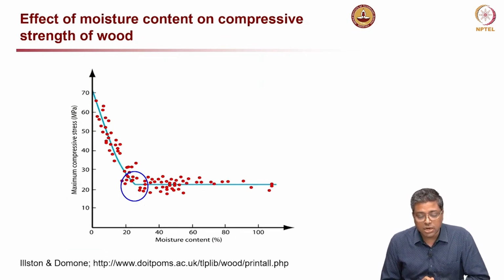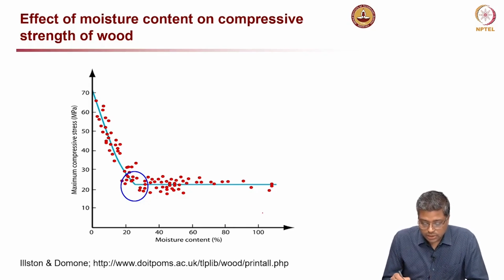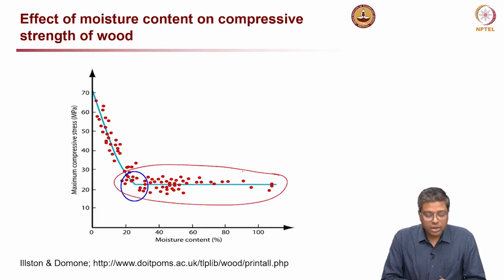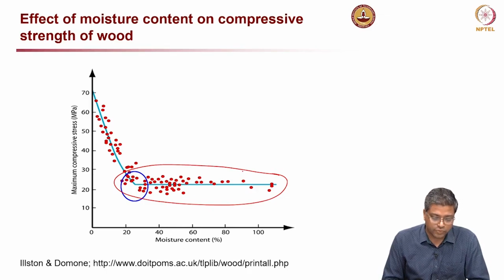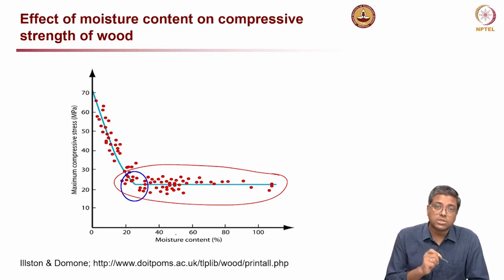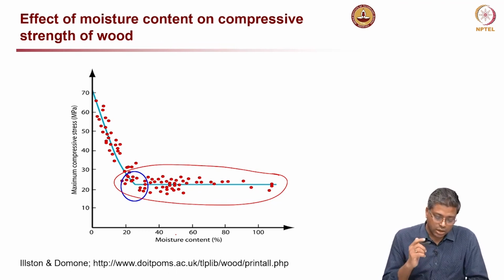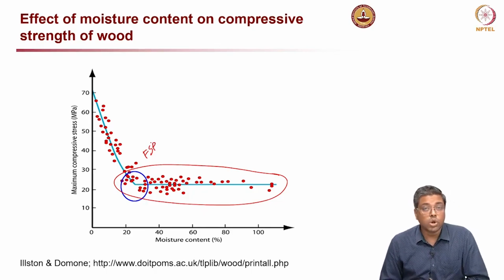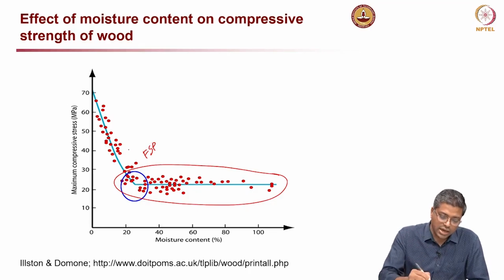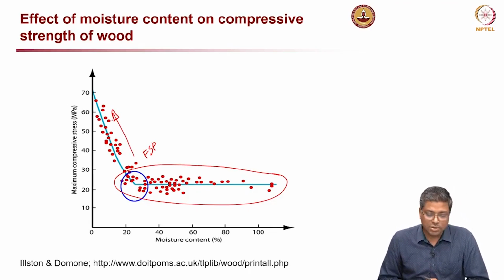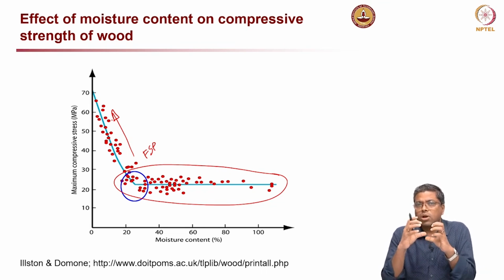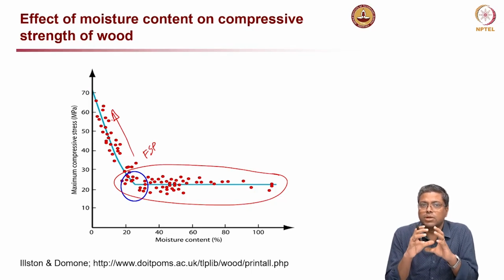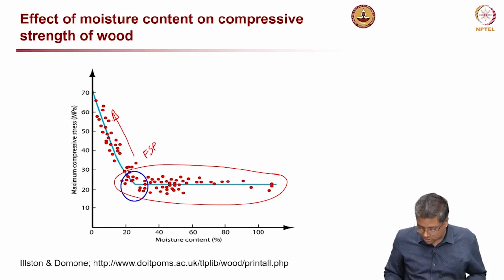Now, effect of moisture content on the compressive strength. So you can see here again the similar picture which I showed earlier. Earlier we looked at the shrinkage property, but this is more on the compressive strength. You can see that there is not much change in the compressive strength of the timber until the moisture content is about the fiber saturation point, or FSP, 20 to 30%. But further drying leads to an increase in the compressive strength, because your cell walls are very tightly packed, and the air content inside the wood is very low, so it can take really high strength.